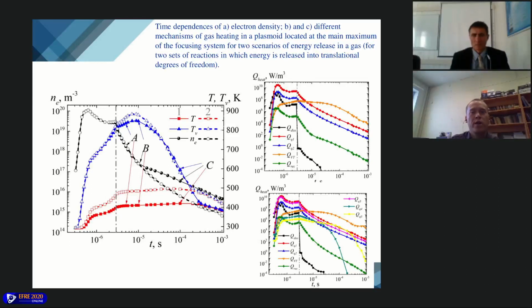In the afterglow phase, the gas temperature continued to rise up to 10 microseconds and is 420 kelvins for the first set of gas heating mechanisms, and up to 70 microseconds and is 500 kelvins for the second set. Further, a slight decrease in temperature is observed up to the time of 270 microseconds. The vibrational and gas temperatures are equalized for both sets of gas heating mechanisms.